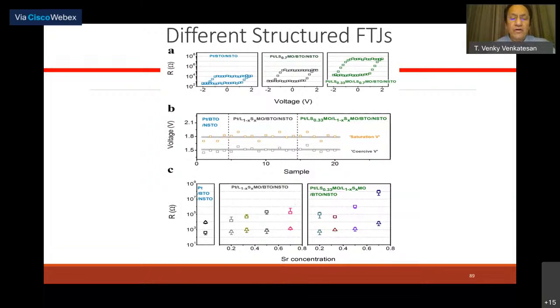Okay. The truth of the matter is, our first commercial GMR devices, the magnetic tunnel junction devices that went into computers, had only a delta R over R of less than 1%, okay? And it still became a commercial technology. So you don't need delta R over R of 10 to the 5. You don't need to create an on-off ratio of 10 to the 5. A smaller on-off ratio is good enough. What you really need is the on-state resistance to be low, so that you can build fast switching devices. And that is our challenge in oxides, because we need a low resistivity substrate, which we don't have.